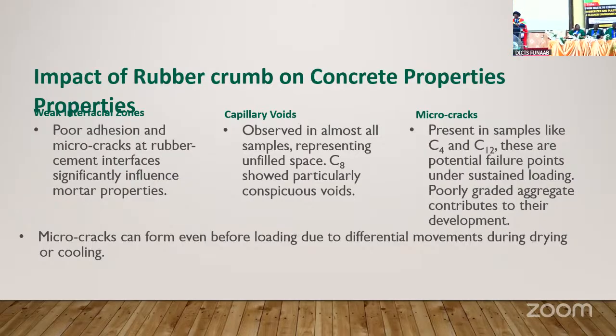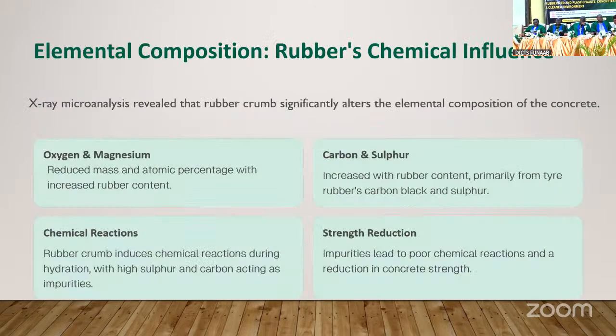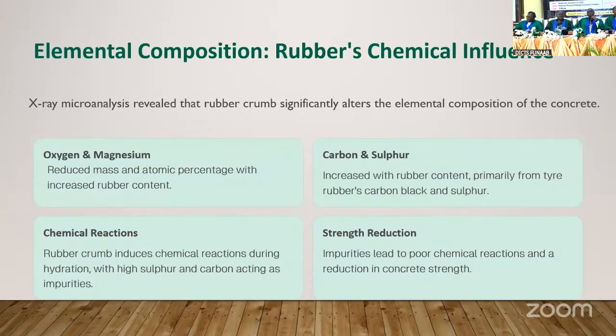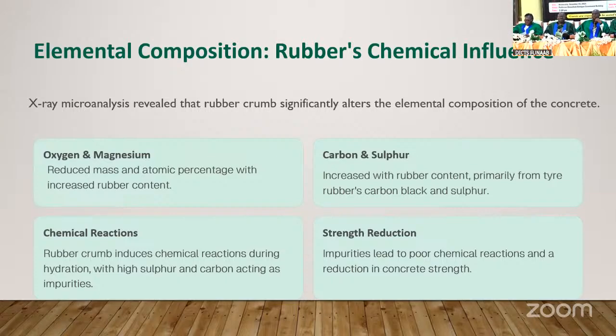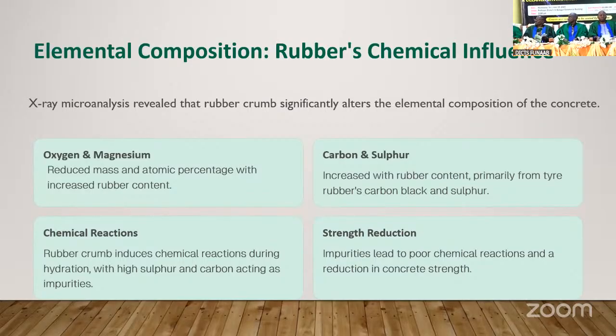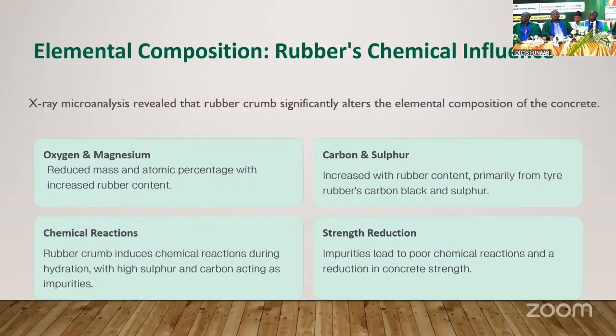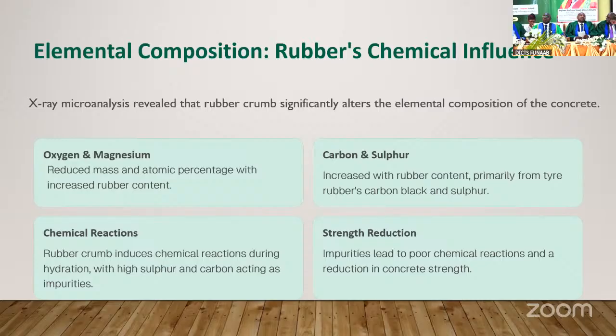Now, the elemental composition: as more rubber crumb was being added to the cement, we have more reduction in the oxygen and magnesium, while we have more carbon and sulfur. The increase in rubber content comes primarily from tire rubber carbon black. This carbon is from the carbon black. The sulfur is from the tire, because sulfur is used to strengthen the rubber for our tires. So it was detected by the machine. The rubber crumb induces chemical reaction during hydration, with high sulfur and carbon acting as impurities. These are impurities in the chemical reaction of concrete.